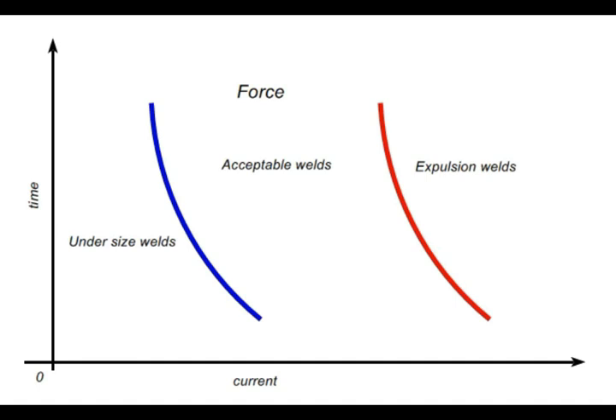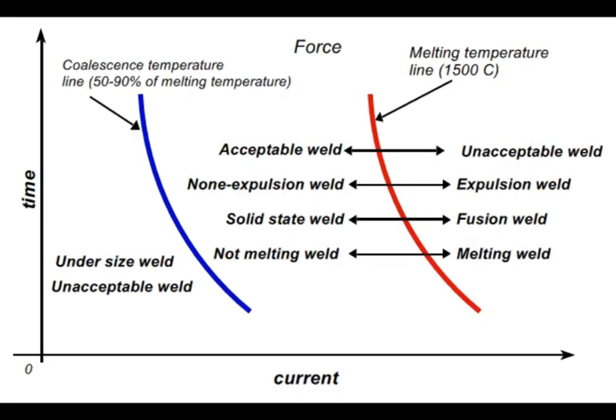The weld lobe normally looks like this. Two curves divide the lobe into three areas. The blue line divides undersized weld or missing weld from acceptable welds. The red line divides the expulsion welds from acceptable welds. Nobody has asked what are the names of those two lines. If on the left of the red line is acceptable weld, on the right of the red line must be unacceptable weld. On the right is expulsion weld, on the left must be non-expulsion weld.